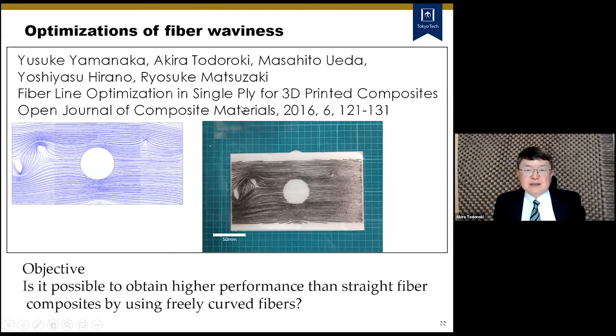And by using this, we optimize the fiber line because we can place these curved carbon fibers. Of course, these cannot be obtained if we use prepreg sheet. Prepreg sheet has straight fibers, but we can curve the fibers for the 3D printers. So by using curved fiber lines, we checked whether we can get higher strength materials or not.